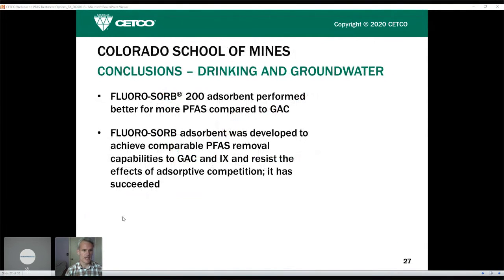You can see the little animation there. So based on these column experiments, what we found was that FLUORO-SORB does have a higher capacity for the perfluoroalkyl acids that were evaluated, and that in some further work that I'll show a little bit of results from, we're above the adsorption capacity for GAC, and it's very similar to ion exchange. And Mike showed some figures earlier that indicated that FLUORO-SORB isn't significantly impacted by other background analytes, maybe a little bit by NOM, but other co-contaminants don't have a big impact on adsorption capacity. Next slide.